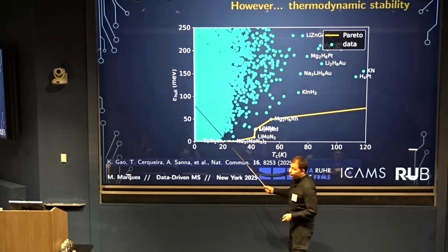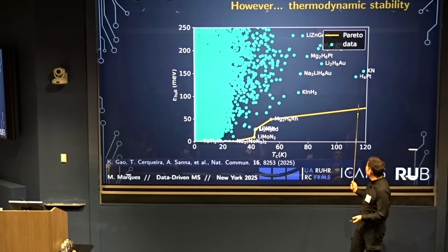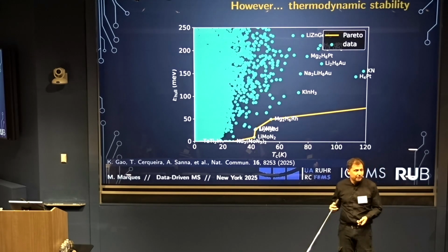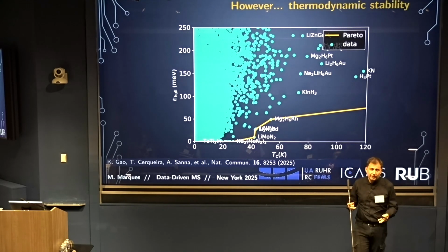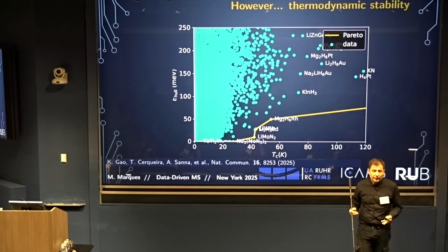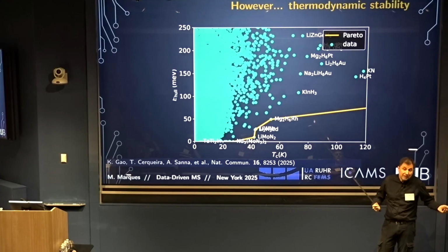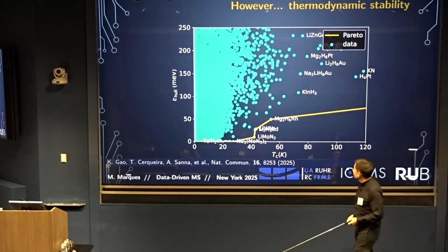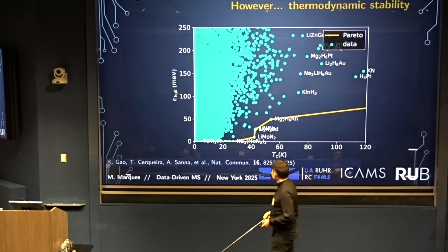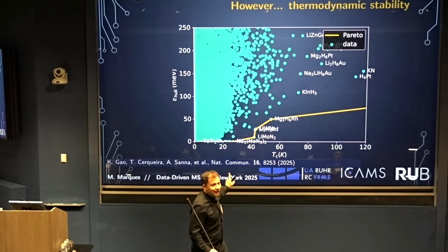So even if from the superconductivity point of view you can have TCs that go well above 100 in the conventional mechanism, the materials that support it are not thermodynamically stable at ambient conditions. Now, can you make them under pressure and quench them? I don't know. That's what is missing. So maybe I should spend just 1 minute saying what we don't have, because we have a lot.